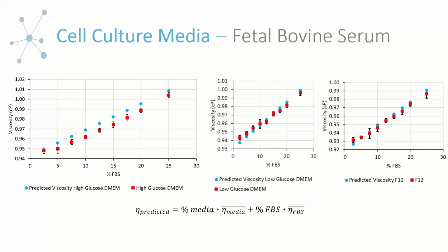And so I was thinking, well, maybe we can predict the viscosity of our supplemental media with FBS. So I just did a simple expected value calculation: the percentage of media times the viscosity of only media plus the percentage of FBS in the formulation times the viscosity of FBS alone. And interestingly, the low glucose DMEM and the F12, which is also low glucose in comparison to the high glucose DMEM, both were able to predict the viscosity quite well. However, with the high glucose DMEM, it was very difficult to predict the viscosity. Although it's a subtle difference, it's still a difference. And I attribute that to some form of interaction between the glucose and the nutrients in the FBS.